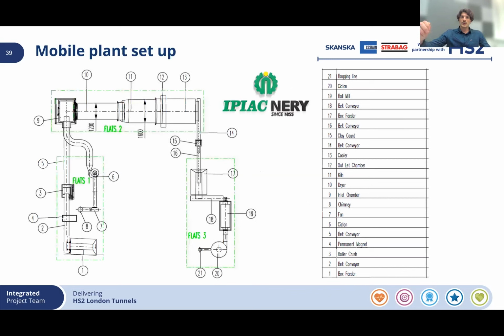Next slide, please. So going forward, what we had in mind was a very ambitious idea. We wanted actually to process the clay directly as it comes out from the tunnel boring machine at the excavation point, at the clay collection point. So we have designed a mobile clay processing facility that involves 21 different pieces of equipment, independent but interconnected, starting from one, where the clay as excavated is inserted in the box feeder, which is part one, and then goes through the whole process with all necessary operations to, in the end, get just a red colored powder that is essentially suitable calcined London clay for use in concrete.